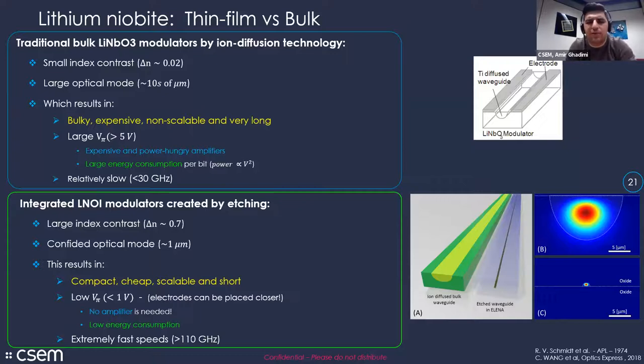So this is where most of the advantages really come in. What we do in LNOI is make the waveguide not by doping, but by etching. With this method, we can create much higher refractive index contrast, confine the light in a much smaller mode volume, and put the electrodes much closer. We can make modulators with V pi below 1 volt. And as a bonus, we gain on speed. The intensity goes up, so we can do nonlinear effects at much lower power.